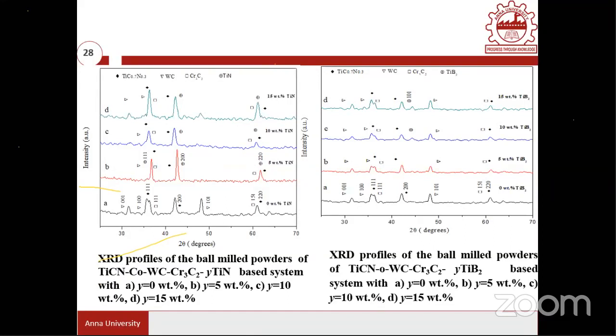Therefore, milling was purely employed for uniform mixing of powders. The uniform mixing was achieved, and there is also a little particle size reduction. That is obvious in the case of ball milling, but no other phases were formed. These phases are the original phases that we have added with the composition.